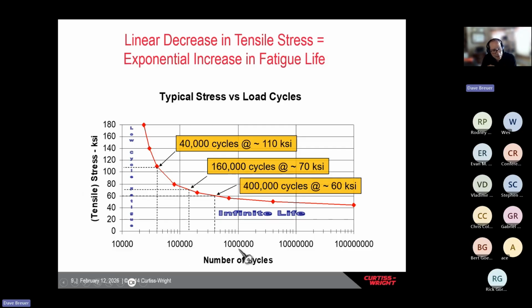So let's use the shot peening effect, canceling out some of the tensile stress. With no shot peening, let's say a component achieves 40,000 life cycles with a cyclic load stress of 110 KSI. If we use shot peening to cancel out some of that tensile stress, the part now experiences 70 KSI of stress. That's about a 35% reduction in stress, and the life quadruples from 40,000 to 160,000.